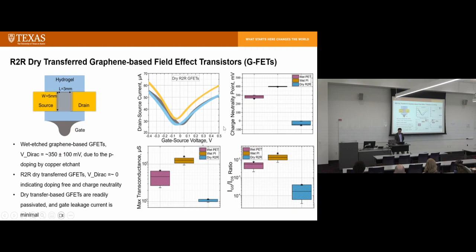So first of all, the charge neutrality point. This voltage you call V Dirac. We did a lot of comparison between dry transferred graphene and wet transferred graphene. For wet transferred graphene, V Dirac is almost all shifted to 350 millivolts, so further away from the zero volt. That's because of doping effect, because you have wet transfer chemical ions, so the ions get doped on the material. So you see a doping effect there. For R2R transferred graphene, our V Dirac is almost close to 0. So this shows our graphene is pure and is not affected by doping.